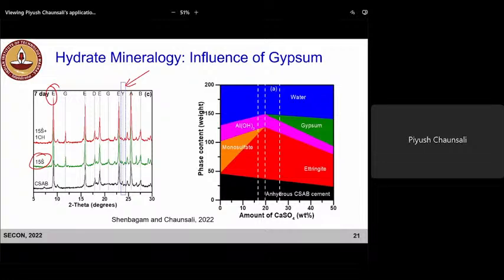On the right side, again, this was developed using GEMS, which can be used for thermodynamic modeling of these systems, and we saw the effect of calcium sulfate addition, right? This modeling predicts that as you increase the amount of calcium sulfate, the amount of monosulfate will decrease and the amount of ettringite will increase. That's what we also saw, and the modeling also predicts that beyond a certain percentage, you will be left with gypsum. And in addition to these phases, you also have aluminum hydroxide.